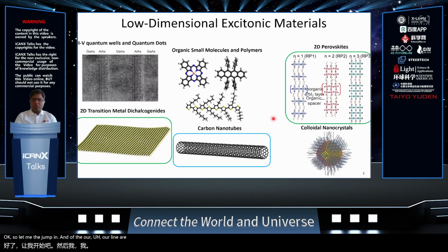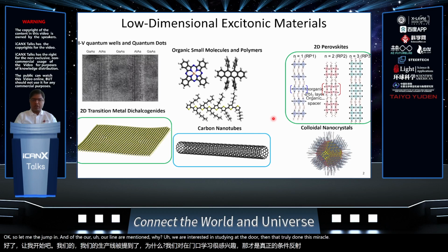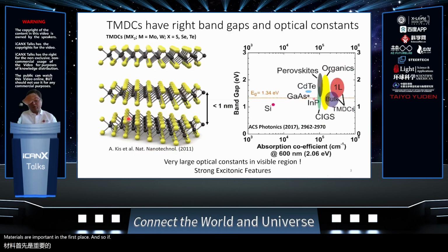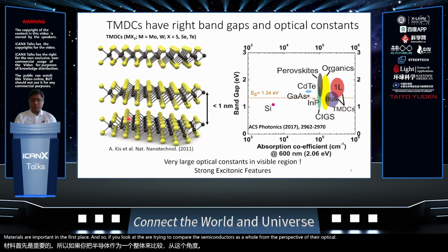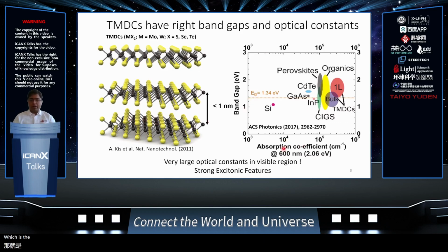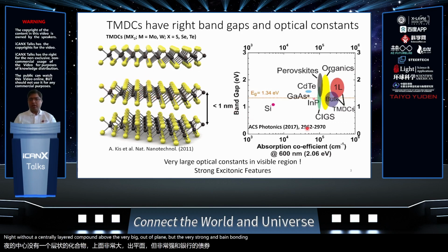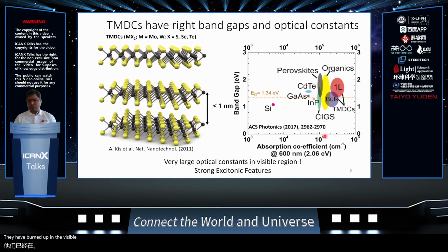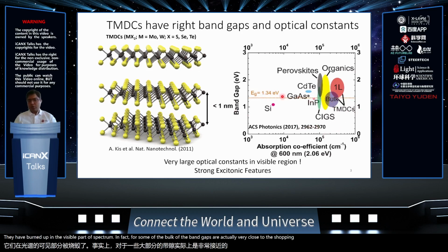outline why we are interested in studying excitons in 2D transition metal dichalcogenides, or why these materials are important in the first place. If you try to compare semiconductors as a whole from the perspective of their optical properties, which is band gap versus absorption coefficient, these transition metal dichalcogenides, which are essentially layered compounds with very weak out-of-plane but very strong in-plane bonding, have band gaps in the visible part of the spectrum. In fact, for some of these bulk materials, the band gaps are very close to the Shockley-Queisser limit, right?